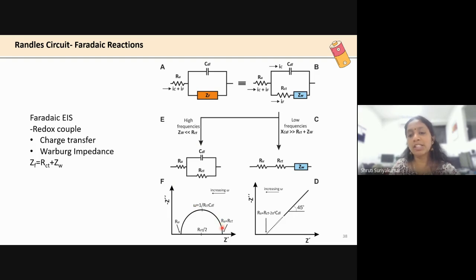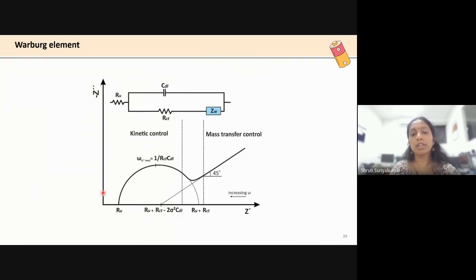And moving on to lower frequencies, this capacitive contribution is going to be very negligible. What you're going to get is close to this equivalent circuit, and that's going to be a slope at 45 degrees. So when you go from high frequency, this is going to happen, and at low frequencies, this is going to happen. So you're getting two different phenomena, and your circuit is going to look something like this. I hope I'm clear. I hope I've conveyed it. You can look at the semicircle here, and you can look at this 45 degree angle here. You get two of these.